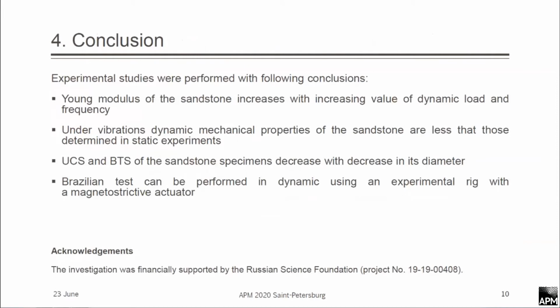So at the end, the conclusions which we made. Young's modulus of the sandstone increases with increased value of dynamic load and frequency. Under vibration, dynamic mechanical properties of sandstone are less than those determined in static experiments. Uniaxial compressive strength and Brazilian tensile stress of the sandstone specimen decrease with increase in its diameter, and the Brazilian test can be performed in dynamics using an experimental rig with a magnetostrictive actuator.